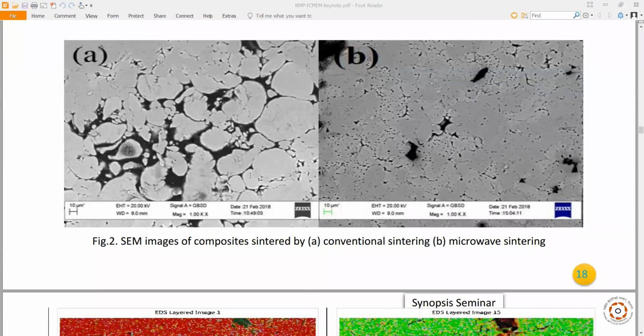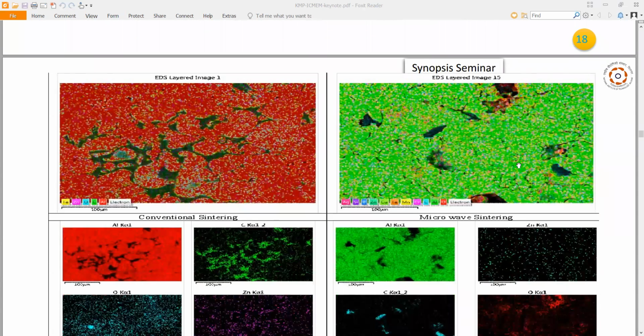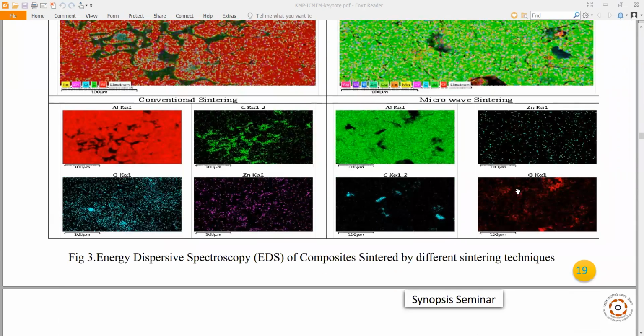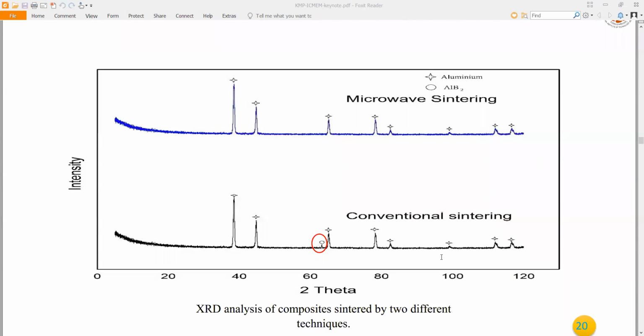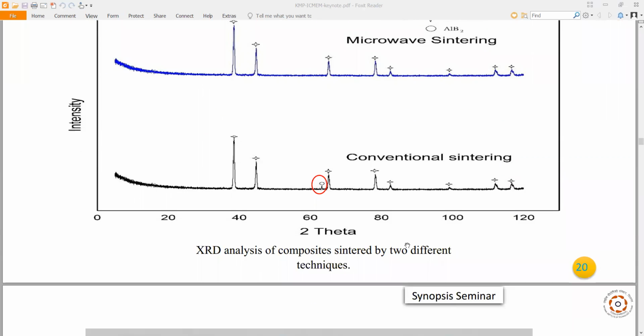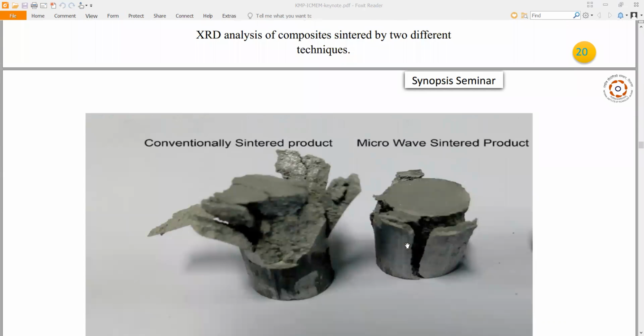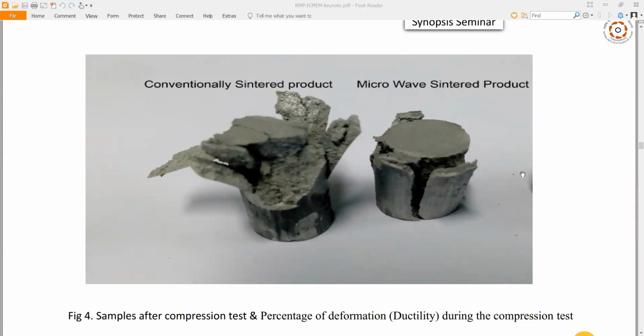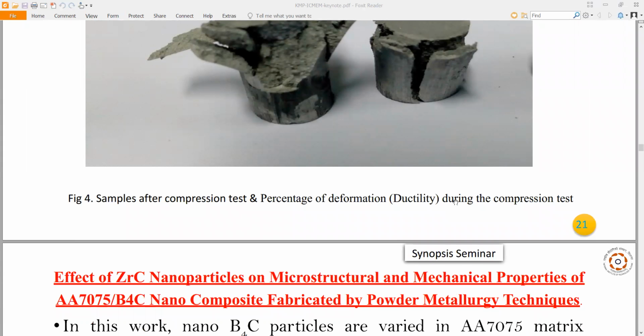Here we can see the diagram: these are SEM images of the composite sintered by conventional sintering, and this is microwave sintering. Here is the energy dispersive EDS analysis of composites sintered by different sintering techniques; this is microwave sintering intensity, and this is conventional sintering. This is the XRD analysis of composites sintered by two different techniques: the conventionally sintered product and the microwave sintered product. This is figure 4, samples after the compression test and percentage of deformation ductility during the compression test.